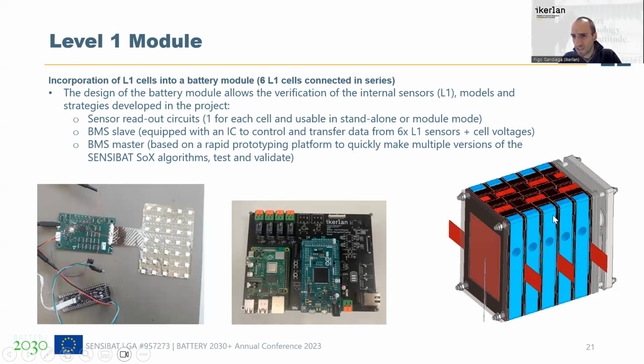So we have 6 cells. The cells are between cooling plates, those blue parts of the cell. Then we have them arranged to have an easier serial connection of the cells. We have one cell to one side, so to the left, and the next one to the right. So we have 3 sensors with a feedthrough area to one side, and the other ones to the other side. Then we have one thermocouple to validate the measurements that we are obtaining from the inside. We have one thermocouple for each cell, and we have 3 pressure sensitive elements on one side of the module to measure the complete pressure that the cells exert on the outside.